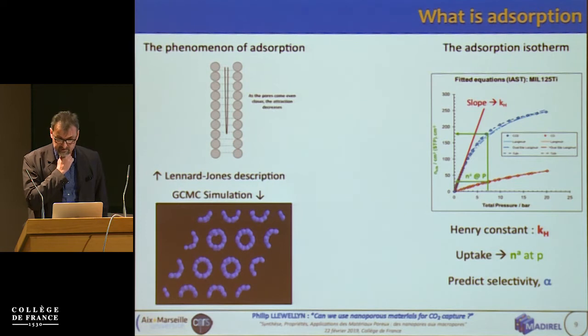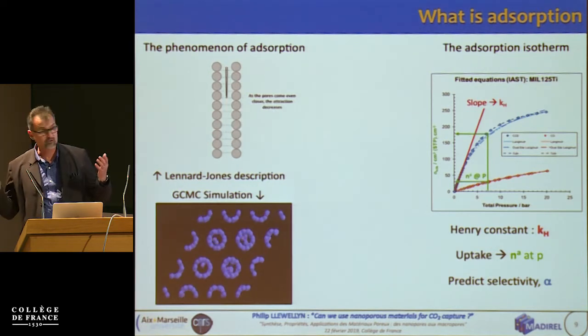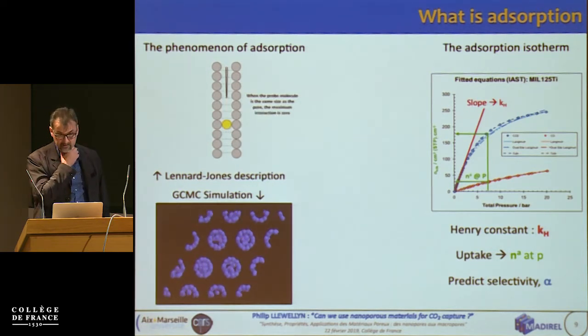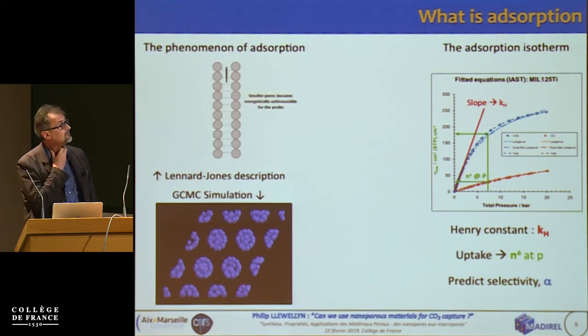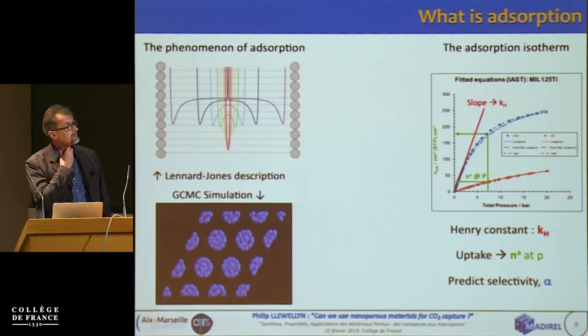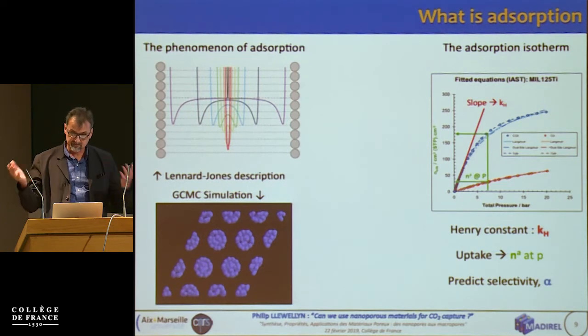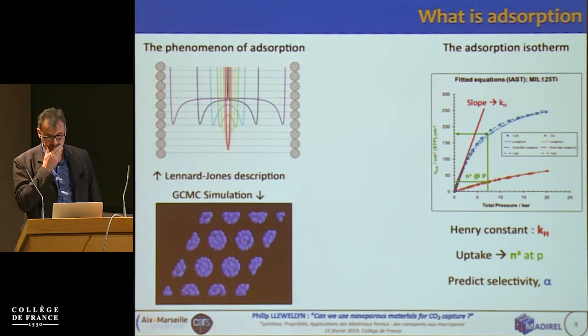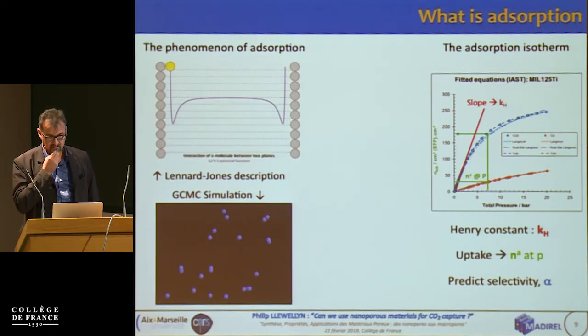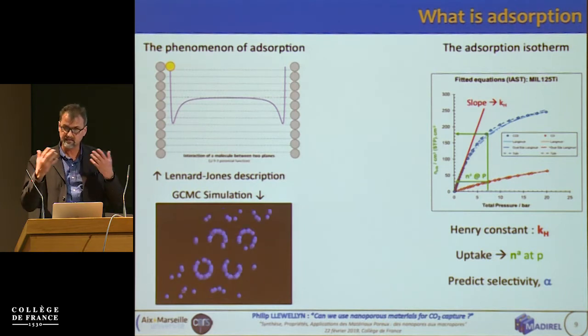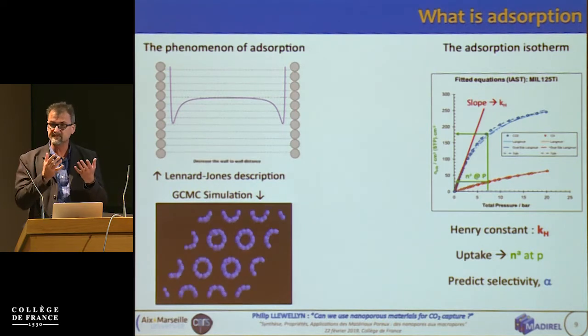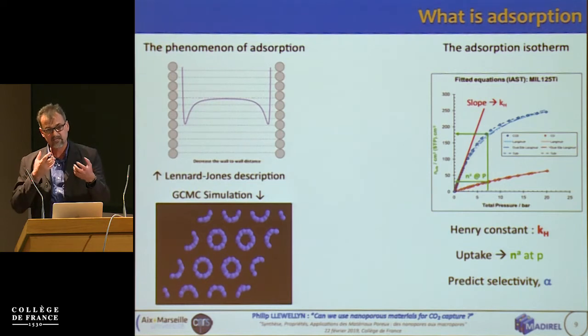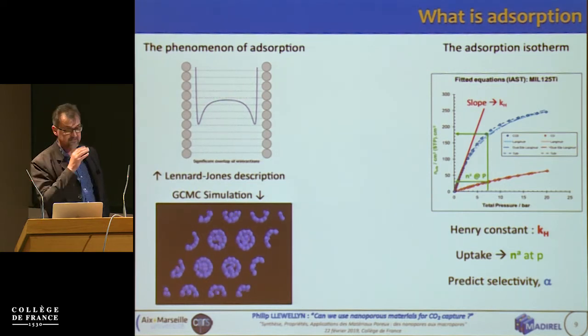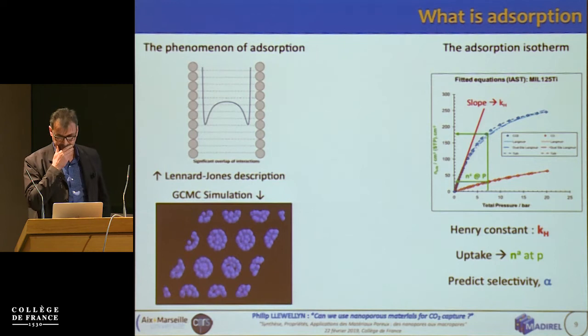What is also of interest is the uptake at a given pressure. So this is what we have in green here. And we can compare the uptakes, for example, of our CO2 and our methane here. And if we have two different isotherms with different gases, we can then start to predict something called selectivity, which is basically the way one material would maybe recover one gas with respect to the other. I don't want to go into details about this, but it's just an easy way to predict.